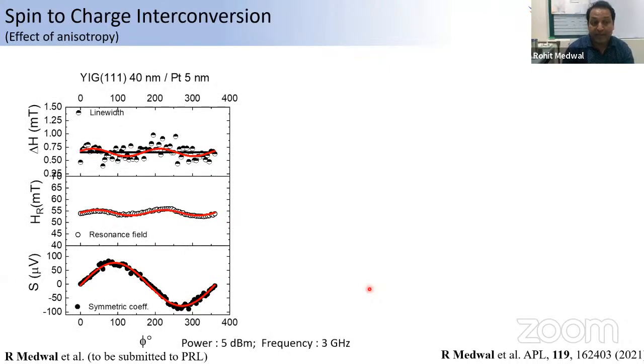One is the spin mixing conductance, and second is the precession cone angle, which I was discussing, and these two contributions are dominating. So for YIG 111, what we observe is that the symmetric component of the voltage, which we are measuring, I can draw the signal here, for the positive and the negative ISHE voltage. When we plot the amplitude of the symmetric component as a function of phi, it should follow sine theta, because the spin current, the direction of spin polarization, and the charge current are orthogonal. So they should follow the sine theta behavior.